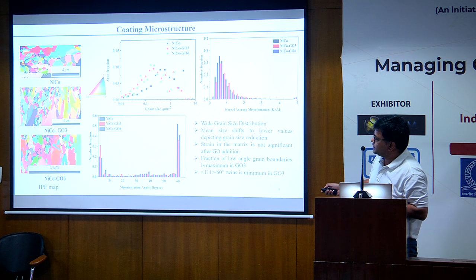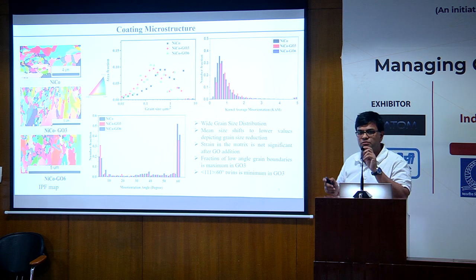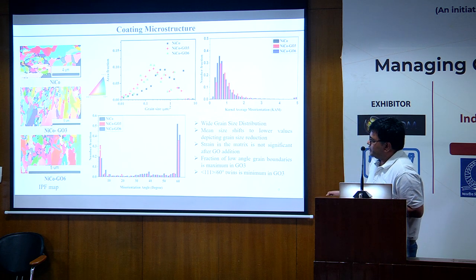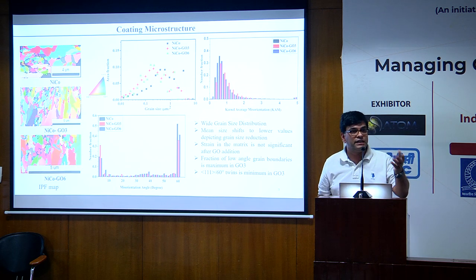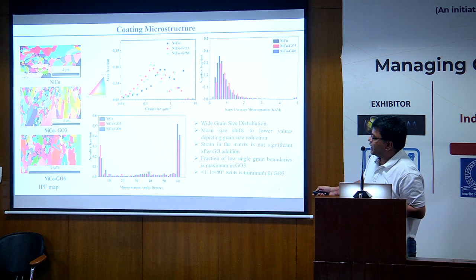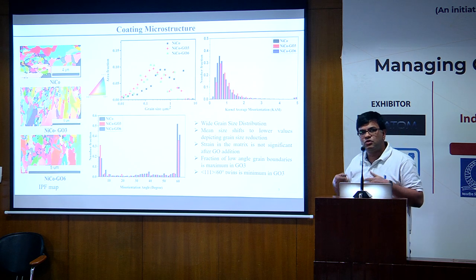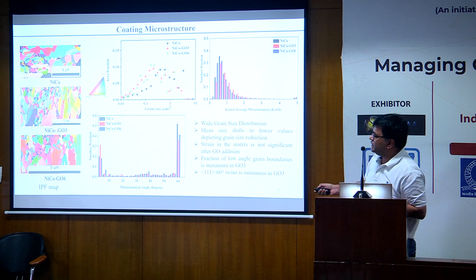The coating with the best corrosion resistance has a texture which is basically having a grain boundary constitution which has the largest number of low angle grain boundaries, which are low energy boundaries. And this is one of the reasons why this coating is giving you a higher corrosion resistance, because these different colors are grains, and the boundary between different colors are basically the grain boundaries. It is a high energy region where the corrosion basically happens mostly. And the interface between these two colored regions, if that interface is of lower energy, then the corrosion will be lesser. Very, very simple.